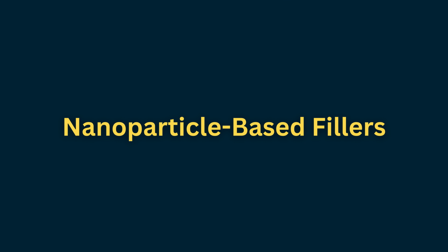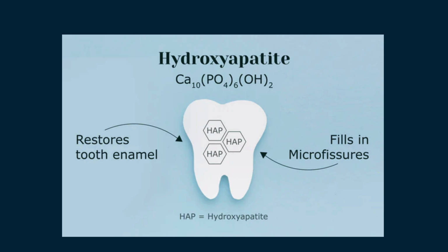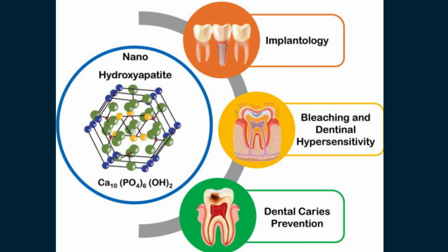Nanoparticle-based fillers. Hydroxyapatite nanoparticles. Hydroxyapatite is the principal mineral component of enamel and dentin, making it an ideal biomimetic filler for dental adhesives. Nano-sized hydroxyapatite particles penetrate dentinal tubules more effectively than larger particles and contribute to the formation of a composite hybrid layer. Hydroxyapatite nanorods formed by directional crystal growth exhibit improved mechanical performance and good colloidal stability. Optimal filler loading ranges from 0.2 to 0.5 wt%.